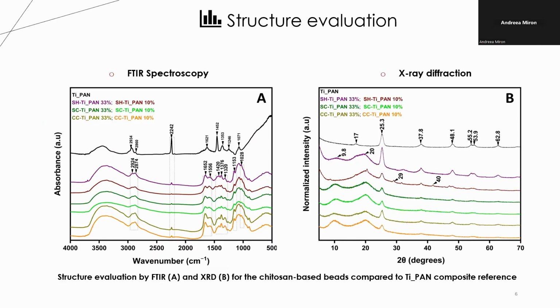The FTIR spectra show the characteristic peaks of both the inorganic organic composite and the chitosan. You can see in this figure the presence of the main characteristic peak for the cyano group, specific for acrylonitrile, which can be observed at 2,242 cm^-1.